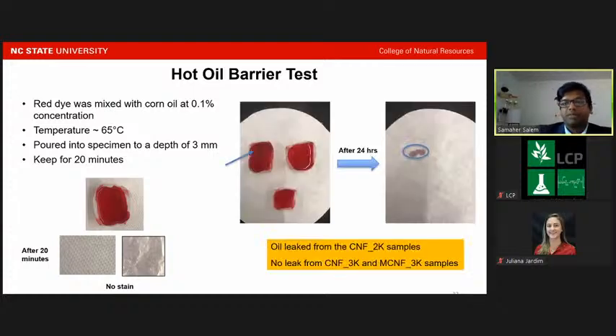Further, we did the test for 24 hours, and we could see that the oil only leaked from the cellulose nanofibrils made at very low energy. But for the nanofibrils produced at higher energy, and also for the modified nanofibrils, there was no leak during the test. Thus, those passed the hot oil barrier test, showing very high oil and grease resistance.